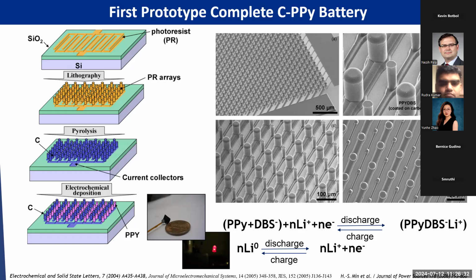And we found that even though polypyrrole is not the best cathode material, we can discharge lithium ion into the polypyrrole. Basically, with this material, the thin film polypyrrole, we can light up an LED if we just check out the half cell.